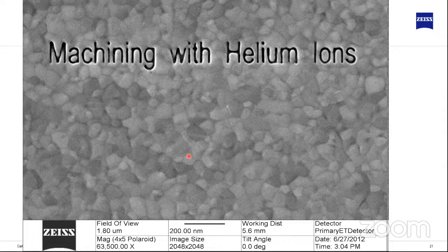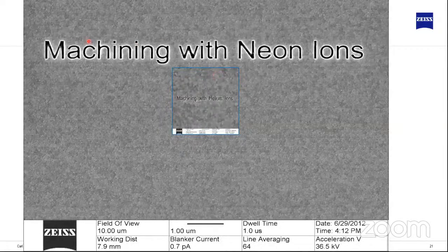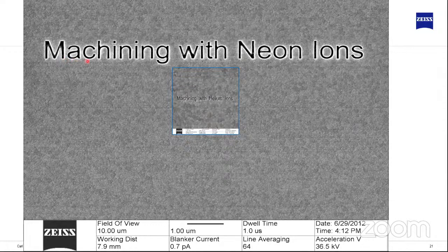We can also use the ion beam if we use a little bit higher currents. We can use the ion beam also for nanomachining, and this is actually what you can get if you just mill something into a gold surface with helium ions. So if we don't take care about what we're doing, we easily get structure sizes below 10 nanometers, and we can do nanomachining with helium. We can do the same with neon ions. There we have a little bit bigger structures, in the range of, let's say, 20 nanometers or smaller.